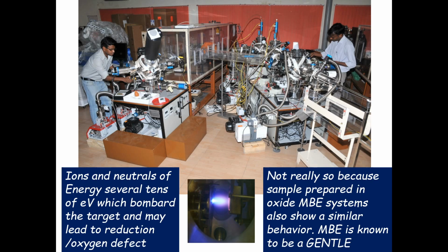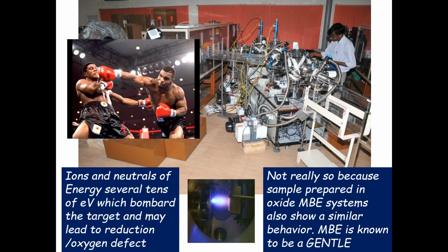There are more machines. But as I told you, this laser ablation process is highly energetic, in the sense that the material that comes out in the plume can have energies as high as 100 electron volt. And when these high energy ions and atoms hit this delicate surface of strontium titanate, it can create a lot of damage. So it's like the right hand punch of Mike Tyson.